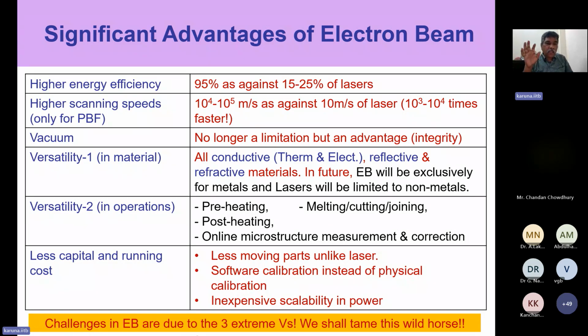You may ask me, why can't we do preheating and post-heating using laser also? See, in electron beam, you scan the layer very fast, in a few milliseconds. But in a few milliseconds you don't get the required melting temperature, because you scan too fast and have transferred very little energy. So in the electron beam system, we keep on scanning the same thing again and again. Because the whole thing is in vacuum, slowly the temperature of the layer rises and at some point melting takes place. Then we stop the beam, and solidification takes place.